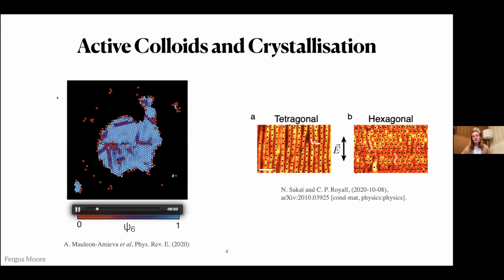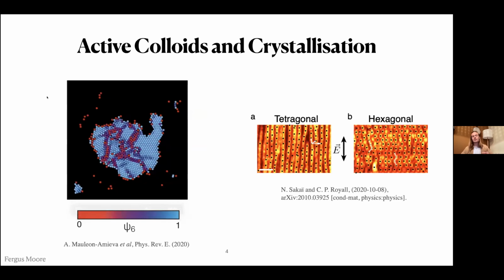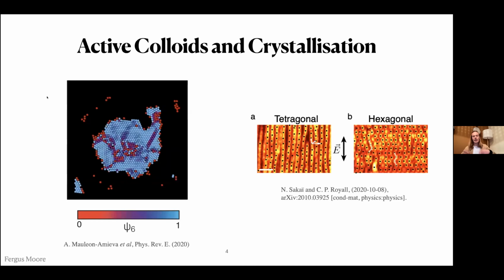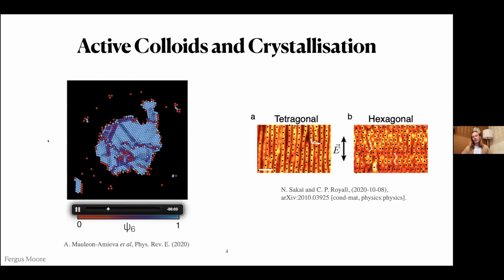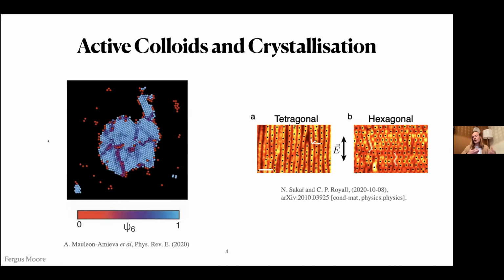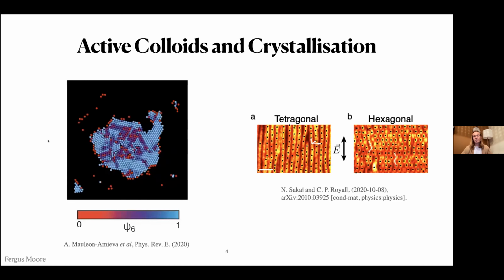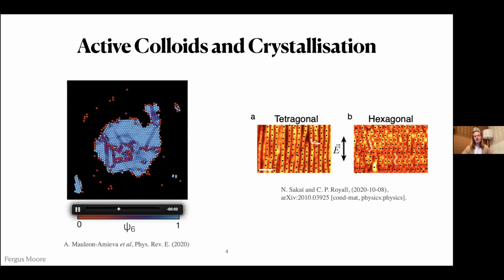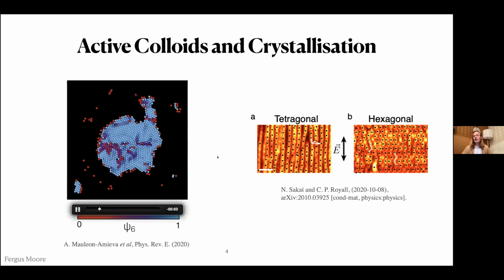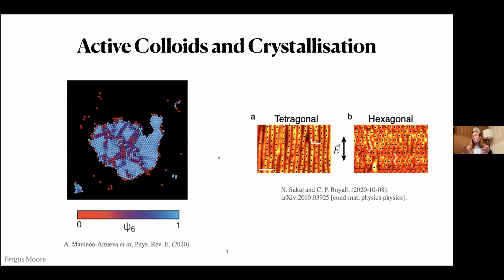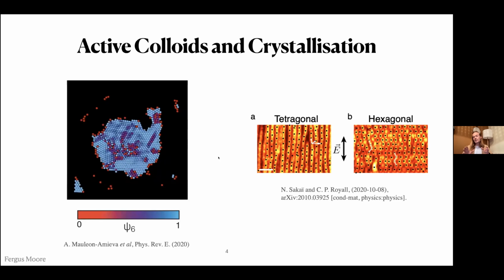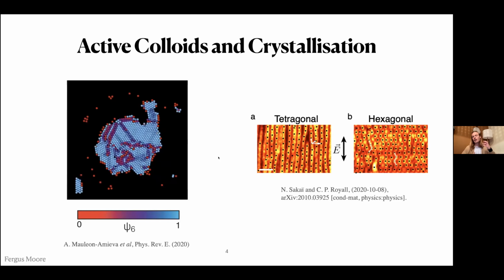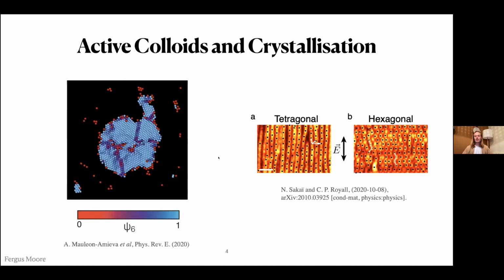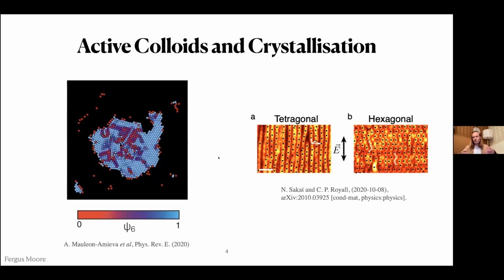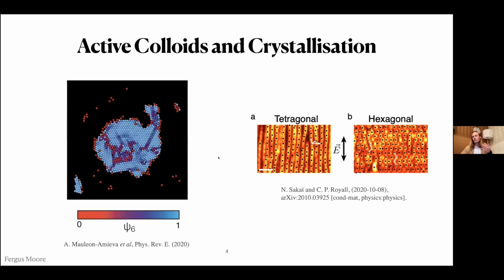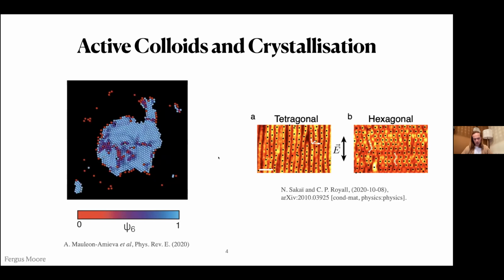So active colloids in particular. Here we have some examples of experiments done in Bristol. We have 2D self-propelling particles here. The color relates to the degree of six-fold symmetry, so you can see these nice hexatic crystals. This is actually experimental data. And on the right, we have 3D active self-propelling particles. These are Janus particles, and not only are they self-propelling and crystallizing in three dimensions, but they also have a dipole, which creates another layer of interesting structure.